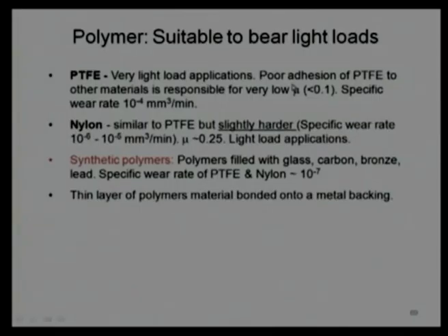But the major thing is they have poor adhesion to metals. That is why they cannot be easily applied. You need to rub it hard or apply more mechanical force to transfer polymers or PTFE from the block to the surface where we want to coat it. They show generally a low coefficient of friction, because they have spherical molecules, and the spherical molecule structure is very advantageous, because they have easy gliding on the surface. That is why they have a low interface shear strength, they make an interface with a low shear strength. However, they have a high wear rate. Their specific wear rate is 10⁻⁴, and units are also mentioned here as mm³ per minute.